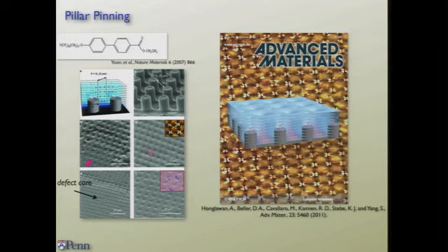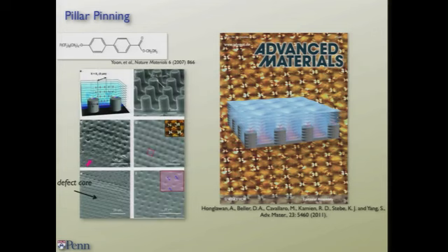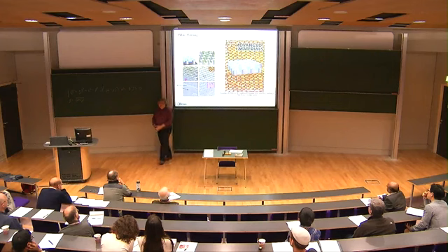And of course, the taller we make the post, the better it is. There's a bigger surface area that's telling them where to sit. We can also do it where we underfill them. Here's something cute. If I go back to the overfilled case. All right, if you have really good eyes, you'll see that between the squares, so here's the squares from the tops of the posts, there's actually a teeny little dot coming from between the posts. So you're starting to get the other ones also.